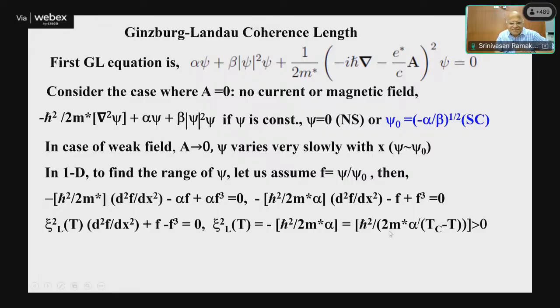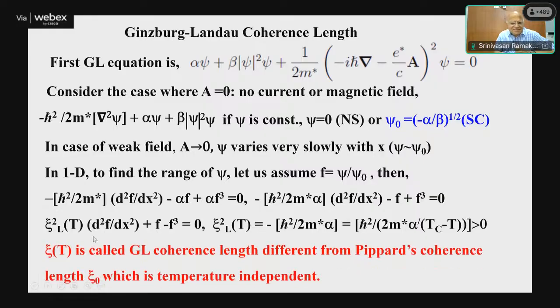And then you can compute this, and what you get is xi squared GL of T, d squared f by dx squared, minus f cubed, is equal to 0. So xi GL squared of T has a length scale. It has the dimensions of length, and this is called the Ginzburg-Landau coherence length. And this is different from the Pippard coherence length, because Pippard's coherence length is temperature independent, whereas this is temperature dependent. Okay, it goes as T minus Tc, and it is greater than zero because we are talking about temperatures less than Tc.